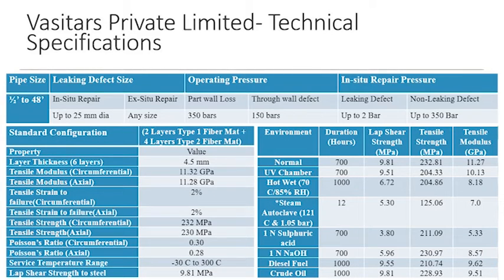Leaking defects can be addressed in-situ for defects of diameter 25 mm and ex-situ for any defect size. The repair is capable of restoring the pipelines to a pressure of 350 bar for part wall loss and up to 150 bar for through wall defects. The repair is capable of sustaining an operating temperature of 300 degrees Celsius.